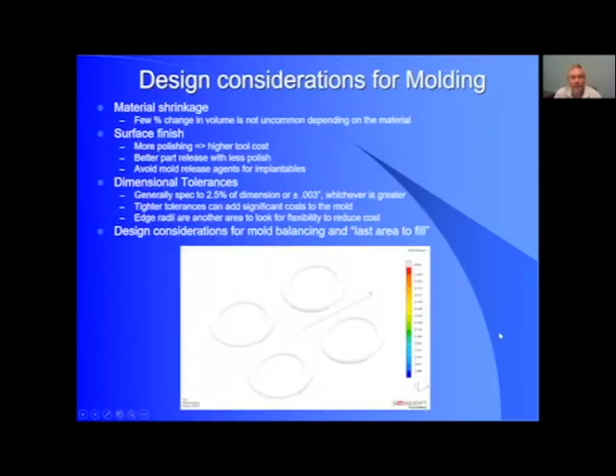So things that we think about in molding are material shrinkage. Some materials can change, as they cool or cure, will change a few percent in volume depending on the material. Surface finish of the mold is important. More polishing typically results in a more expensive tool, and you often get better part release with less polish because it'll tend to want to kind of fuse in and there's very little gaps for the material to want to release. Because you also typically don't want to use any sort of chemical mold release agents to release your parts.